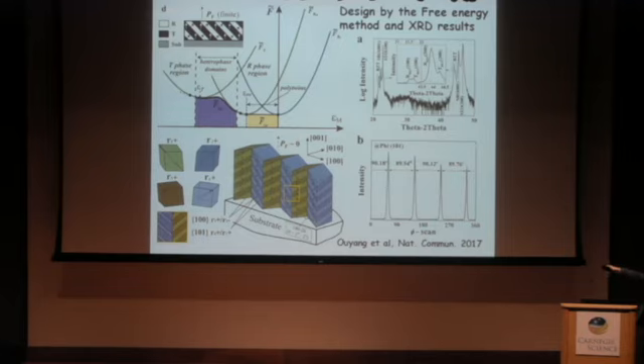In this case, you have a finite remnant polarization, but you probably can harvest a little bit more energy density because when you apply the electric field, you're going to change one phase into the other. That costs you extra electric energy. But if you have a very thick film, you're going to have a dominant rhombohedral structure, hopefully, if we can have this hierarchical polydomain. So in this case, your apparent polarization is close to zero, and this polydomain structure can ideally have close to 100% charge-discharge efficiency, like I just described in the beginning. So in this case, not only do we need to grow films of different thickness, but we also tune the film misfit by growing them on different substrates.